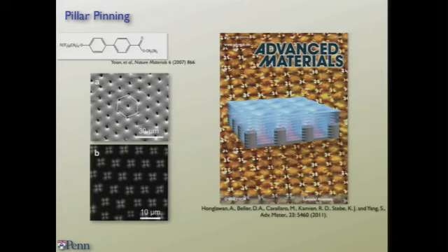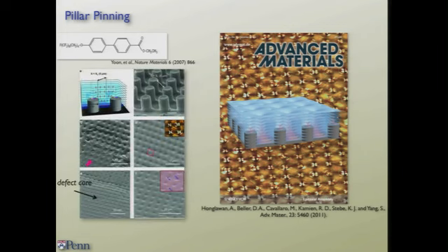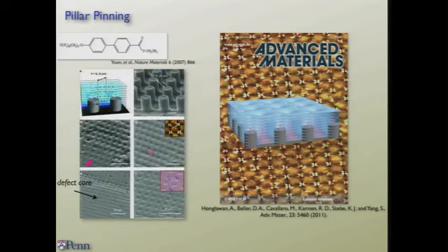And we did, right, so here's the same molecule. And we verified that we get a triangular lattice if we leave them alone. But then we put them on these microposts. Here is the overfilled case where you get this pattern, now a square pattern. Not only is it square instead of triangular, it's the wrong spacing. Left to itself, it would have 30 micron-ish spacing. We put our posts much closer together, see, 2 or 3 microns. So we can actually take over. We can tell those focal conic domains where to sit. Right? This is strong enough to let them sit.